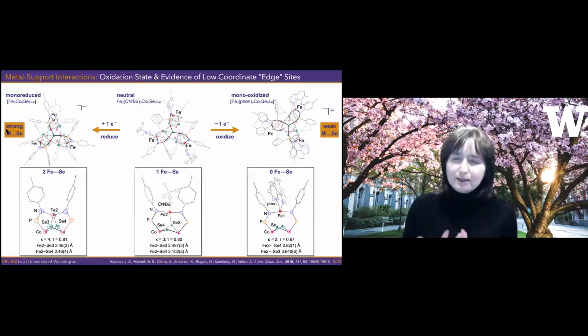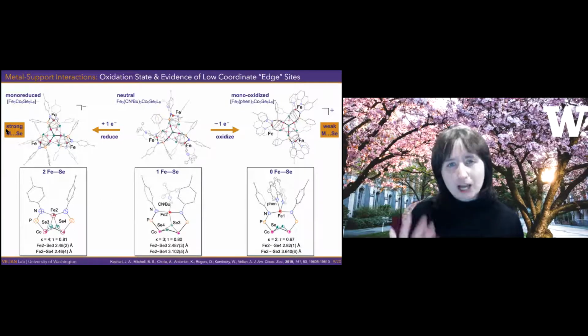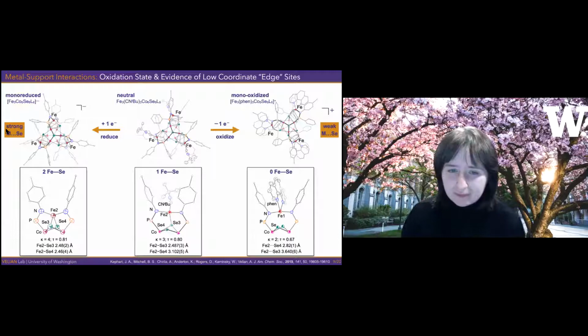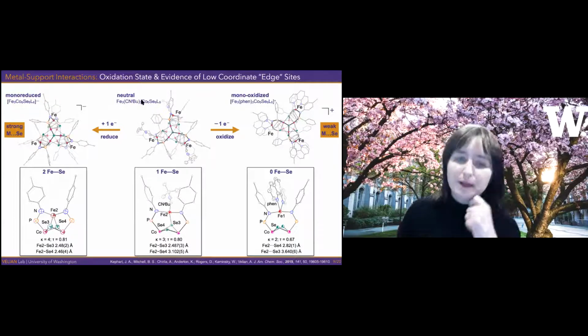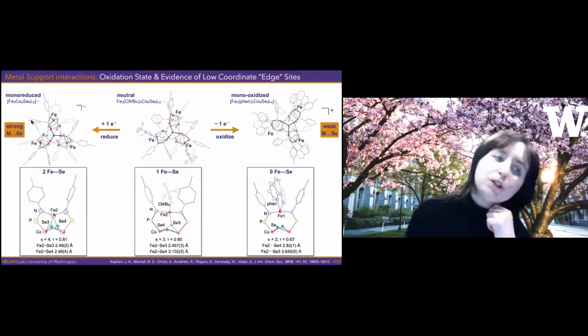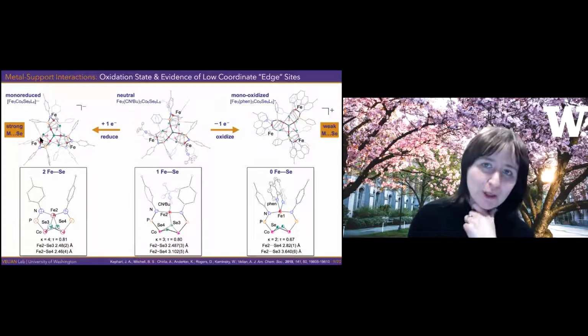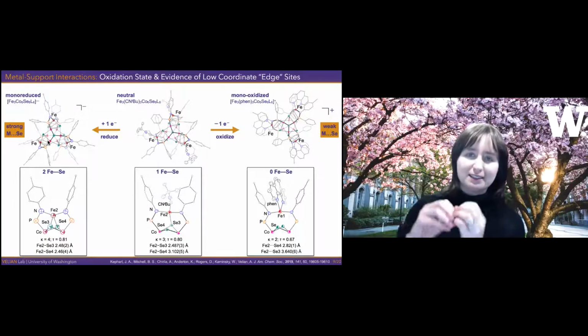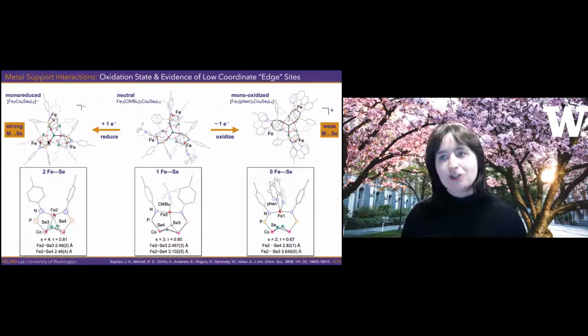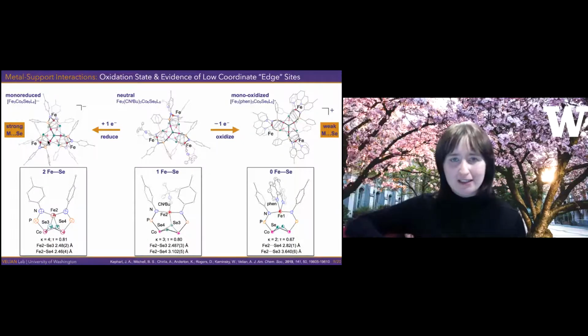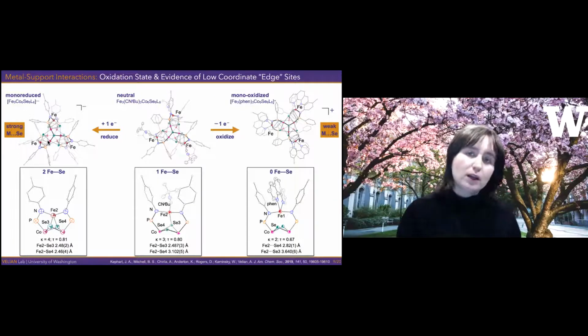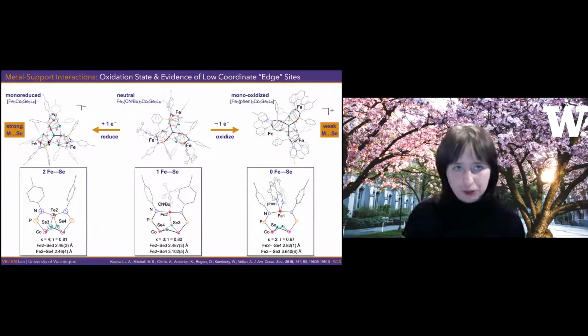And what this hinted or foreshadowed for us is that the electronic structure must be such that when you take an electron out, it's coming out from the cluster core, and when you put an electron in, you're probably also putting it into the core. So then the seleniums become less electron rich, and the iron prefers to bind to external ligands, or the cluster becomes more electron rich, the seleniums are better ligands, and then they outcompete external ones.